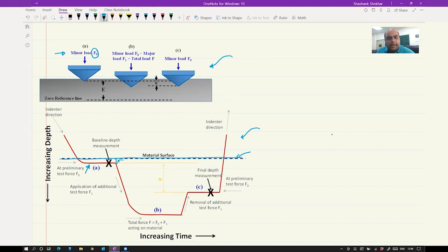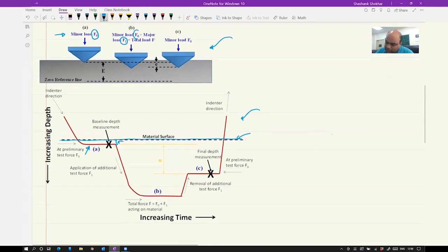Now you apply a major load onto the minor load. So you have a minor load of F0, a major load of F1, and a total load of F, which is equal to F0 plus F1. You reach some distance here, which corresponds to the depth at a load of F equal to F0 plus F1. This is the total depth from the surface. Now you remove the additional test force F1, so you are removing the major load. Your indentation direction is shown by the dotted arrow, which is how it goes with respect to time.